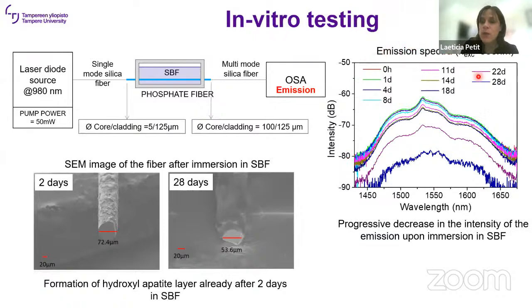The fiber was immersed up to 28 days, and you have the emission band of erbium, the typical emission band of erbium, centered at 1.5 micron. And over time, we see a decrease in the intensity of the emission from the erbium.